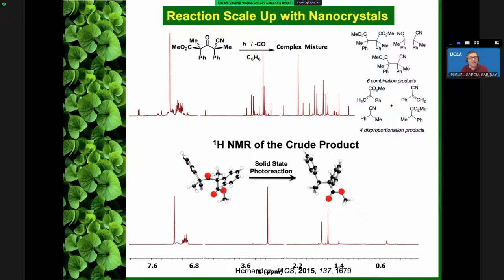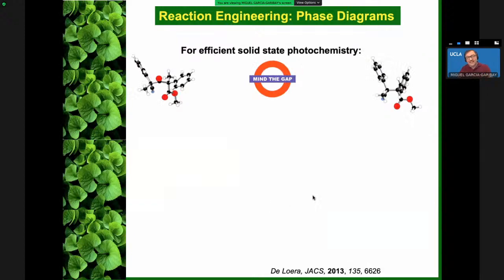When you do it in a crystal, what you see in the bottom, you see the proton NMR of the crude sample, which is just perfect. If you just look at the methoxy signal in the middle of the spectrum here, you can see that corresponds to that carbon, and that tells us that the reaction in the solid state in the nanocrystals is just perfect, which is wonderful. Now, let me tell you that for these reactions to be so good, there are a couple of things that we need to consider. These are important. We need to mind the gap.